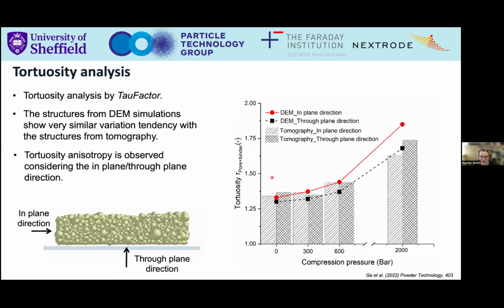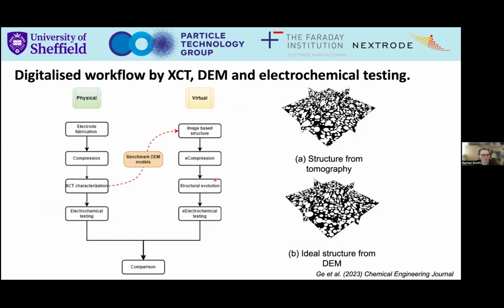The interesting thing here is that when we compact the electrode, we change the through plane direction of the tortuosity in a different way to the in plane direction. And so that's also really important to capture. And this is a demonstration that we can capture this quite well.